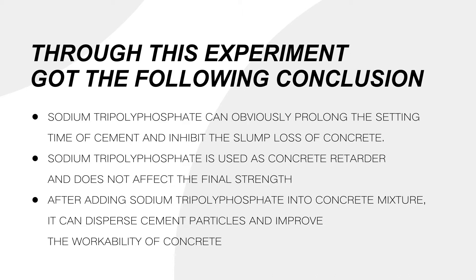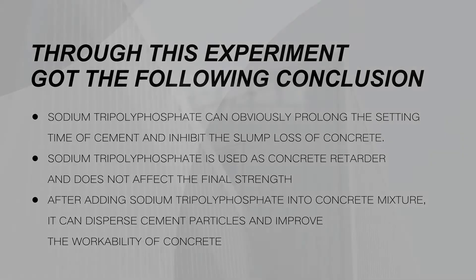2. Sodium tripolyphosphate is used as a concrete retarder and does not affect the final strength. 3. After adding sodium tripolyphosphate into a concrete mixture, it can disperse cement particles and improve the workability of concrete.